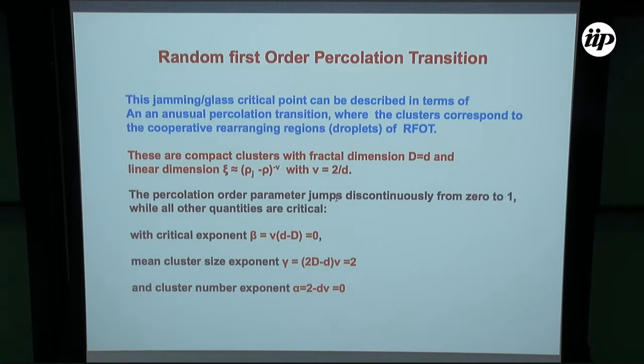Okay, so now if we want to understand what the critical behavior is at this jamming transition, we have developed some kind of percolation. We call it random first order percolation transition, because this type of percolation that I'm going to show you now describes the critical point of the random first order transition. And this percolation is essentially percolation done with the clusters which correspond to the cooperative rearranging regions, which are the droplets of the random first order transition. What are these clusters?